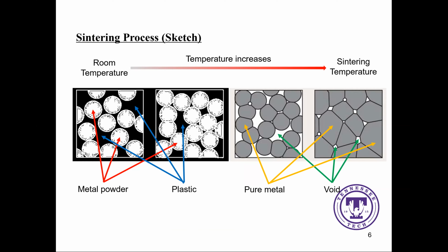This is a sketch of the sintering process. We see the metal powders in a plastic matrix. We increase the temperature from the room temperature to a sintering temperature. The sintering temperature is a little lower than the melting temperature of the metal. For example, the melting temperature of the bronze is 900 degrees Celsius, so our sintering temperature is around 890 degrees Celsius, just a little lower. And in this process, the plastic is melting out and the metal powders gather together to form the final part, which is a pure metal. But at the end, the final part has some internal void. This cannot be avoided.